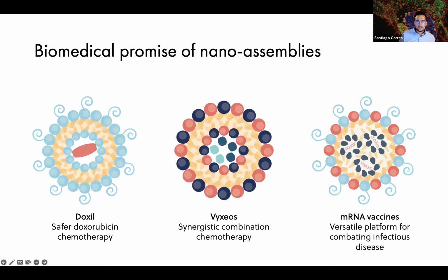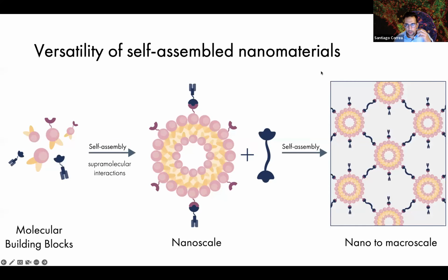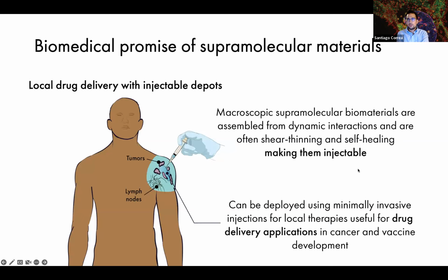But while these types of nanomedicines have been making strides in the clinic, over the past 20 years or so, we're still seeing this emerging area of nanoparticle-based assemblies. This is an area that's fairly recent and has some really exciting implications for local drug delivery. The reason is that, like other supramolecular macroscopic materials, nanoparticle-based assemblies have useful mechanical properties due to the dynamic and reversible interactions that govern their self-assembly. From a clinical perspective, one of their major advantages is that we can inject these hydrogels directly into target tissues, which has opened a lot of doors in local drug delivery, in particular with regards to immune engineering and tissue engineering.